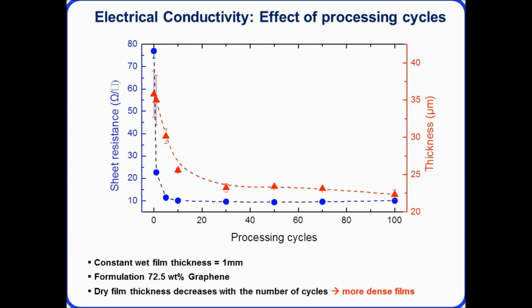of resulting films. So here we've kept a constant wet film thickness of the ink, and we measure the sheet resistance as a function of these process cycles. So what you can see, after even 5 to 10 cycles, we have pretty consistent sheet resistance. However, it's the thickness of the resulting film that changes.